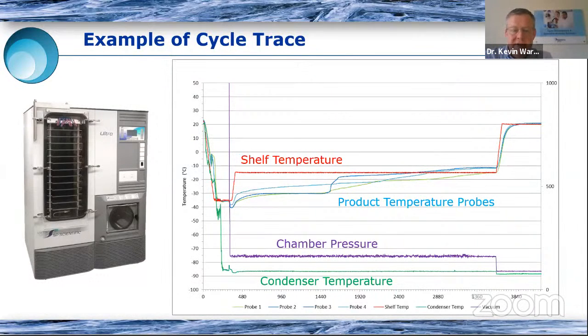We might also be interested in the condenser temperature. So on the bottom right of the freeze dryer, this chamber here, the cylindrical smooth wall chamber is our condenser. So that's where we're going to deposit the vapor that's coming off of the product. Now, the one thing we need to make sure is that this is below the temperature of the product in order to attract the water to it. And so we traditionally cannot control the condenser temperature. We can't dial in a set point, but it typically will be maintained at its lowest possible point throughout the cycle, but we typically monitor it in order to make sure that everything is running well.